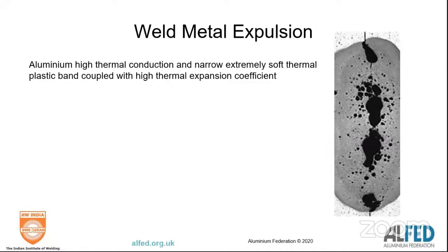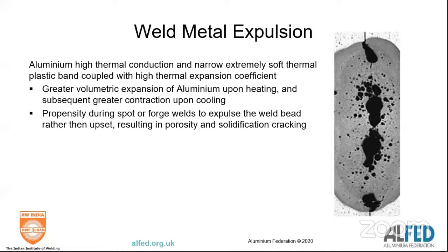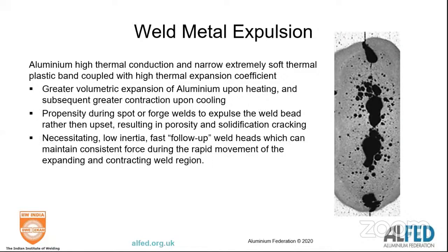Again, we've got high thermal conductivity, very narrow, soft thermal plastic band, high thermal expansion, big volumetric changes. So there's a high risk when you're spot welding aluminium that you're going to squirt out your metal rather than solidify it. So with spot welding, you actually need fast heat up and then maintain the constant pressure to form your welds.